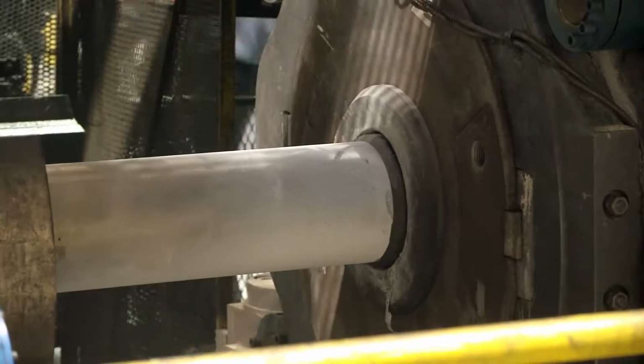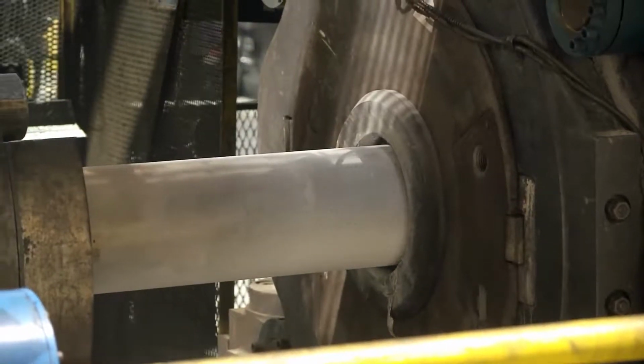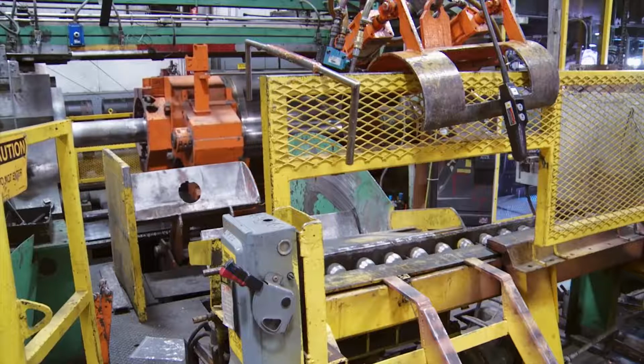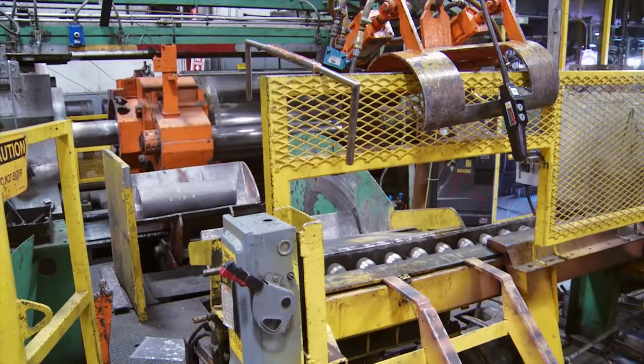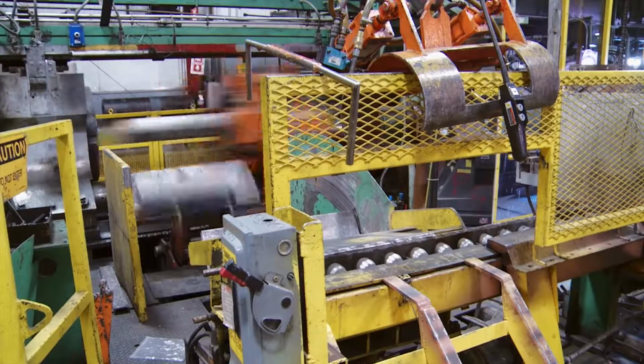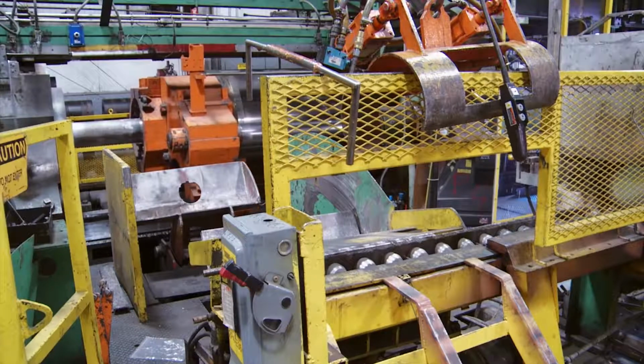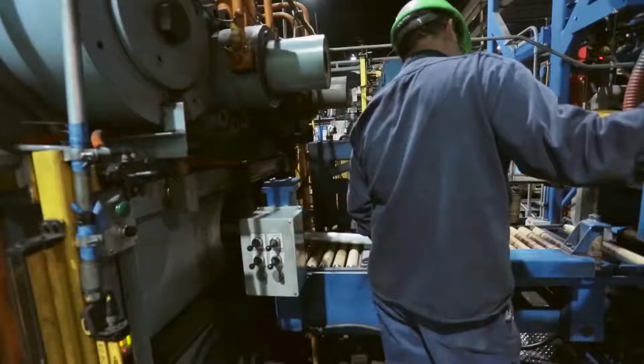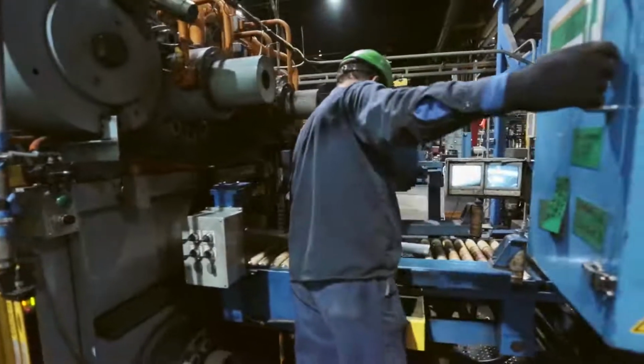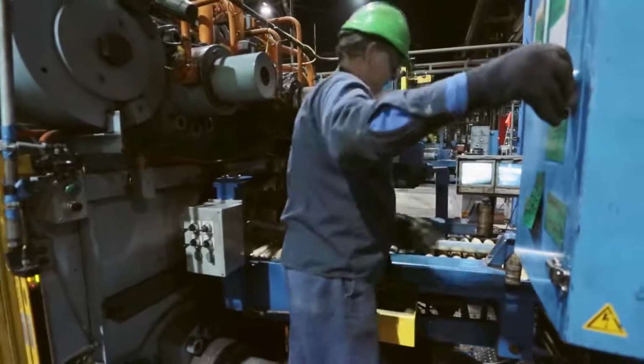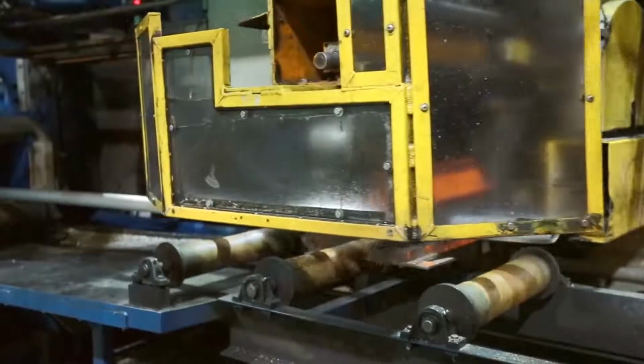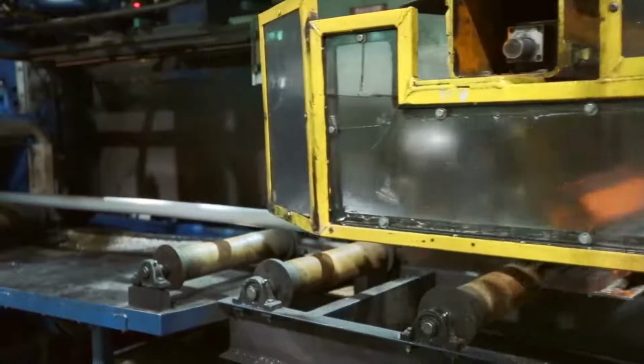With the direct extrusion process, the center of the billet flows faster than the metal at the perimeter. That is because of the tremendous friction at the container walls. Friction is a major energy cost of extrusion. Some calculations have friction accounting for half of the total energy drain on our business. Friction also robs die face pressure and can vary extrusion temperatures, which in turn affects dimensional control of the finished extrusion.